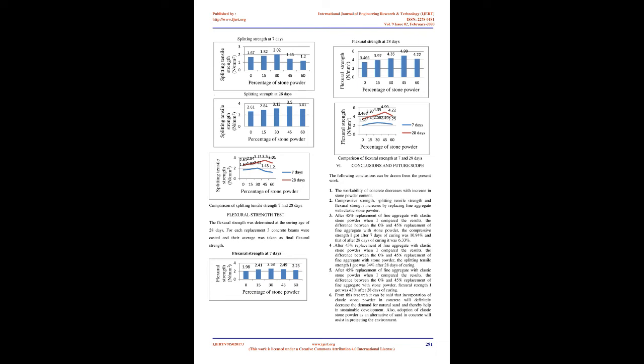According to IS code 516-1959, the specimen is tested under 2-point loading over an effective span of 600 mm divided into 3 equal parts and restrained. The load shall be applied at the rate of 400 kg per minute for the 15.0 cm specimen and at a rate of 180 kg per minute for the 10 cm specimen.